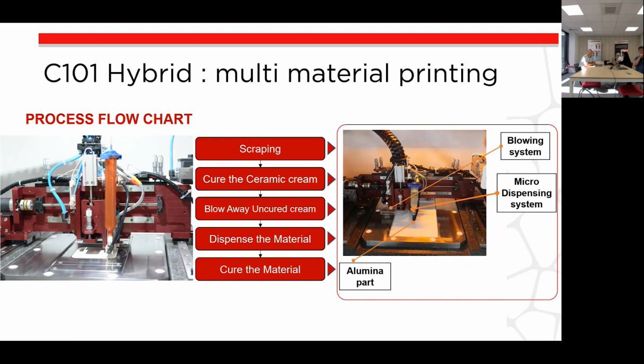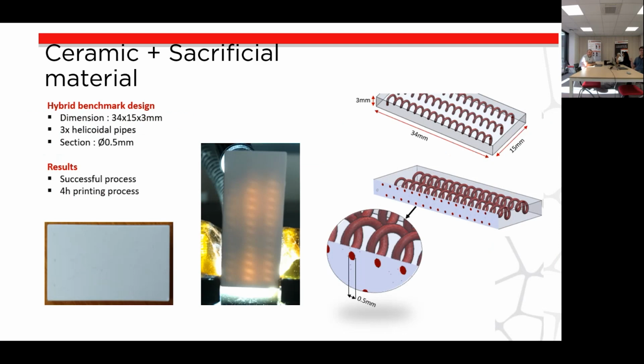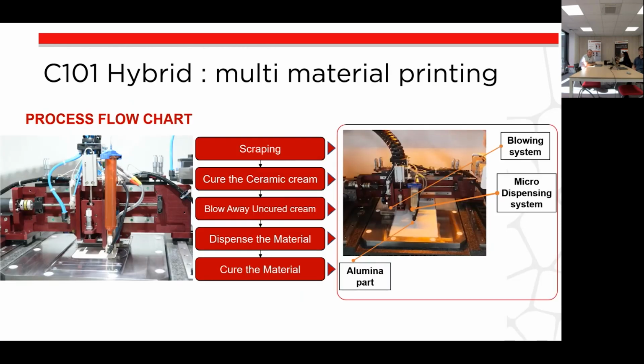So that's the picture that you see on the right-hand side of the screen, the little plexiglass item on the left of the carriage. That's a blowing nozzle. So the idea of this is to blow away any uncured material and to create a via or void where you would dispense your second material. So once you've blown away all the uncured material, you will then dispense your second material. That could be a sacrificial, or it could be another material like tungsten, for example. Once you've dispensed that material, you would then need to cure it or not, depending on what you want to do. In this case, if you're using sacrificial, for example, you would then need to cure it and then go back to the start of the flow chart, scrape another layer, etc., etc.